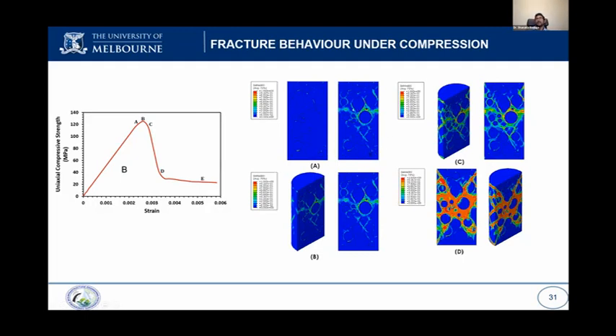Then the B, what we found, after damage at ITZ, the damage is propagating around the ITZ. But the failure is when the cylinder is failing in a diagonal. So now the damage cannot go around the aggregate, because ITZ is, as I mentioned, stronger. So what will happen then, the damage is going through the mortar, then it propagates through the aggregate.